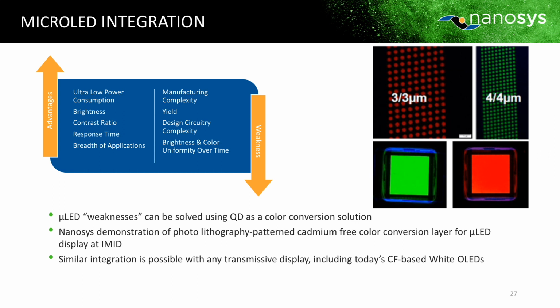You can see here with our photolithography system, QDPR, we're getting very good resolution at 3 micron. With the inks, they have an inherent limitation that's associated to the drop size and how the inkjet produces that drop size. But we've done things at 80 microns, 50 microns, and even some proof of concept down to about 30 microns. So those are the 2 trade-offs between those 2 different material systems, but both for color conversion.